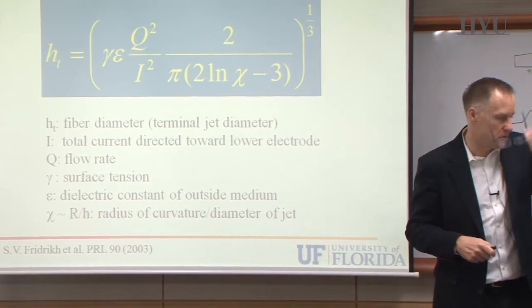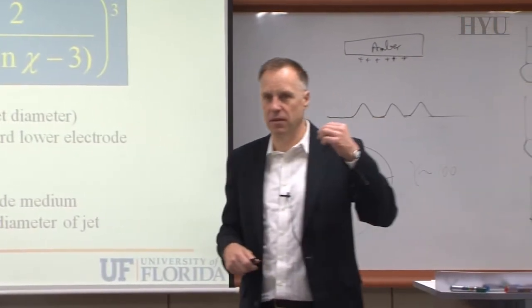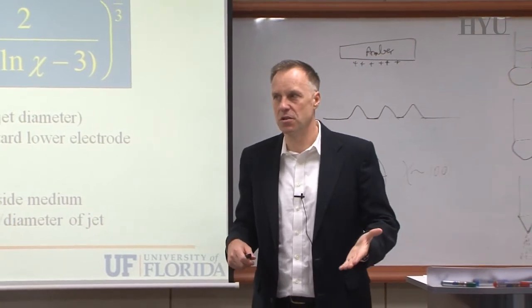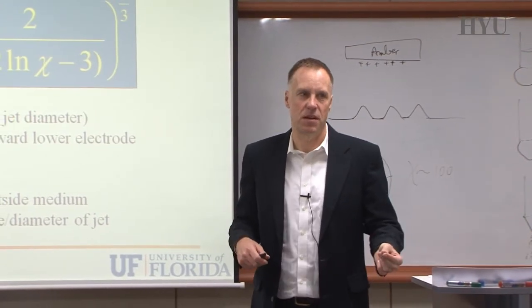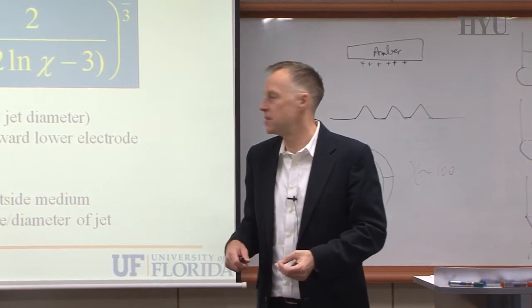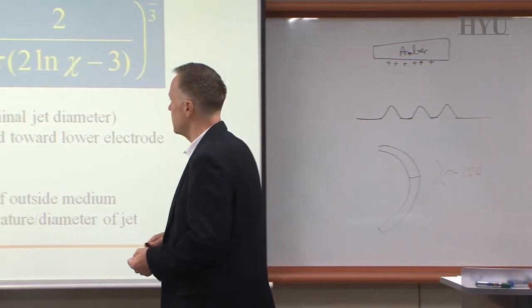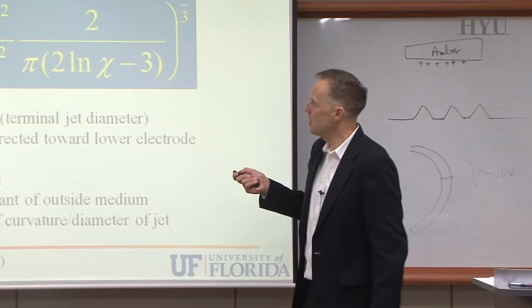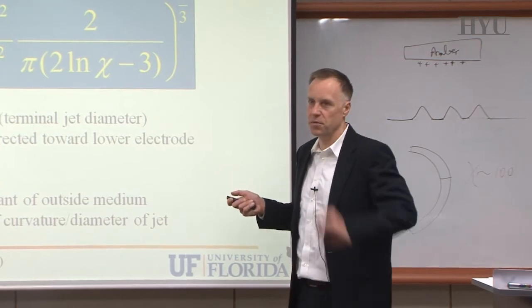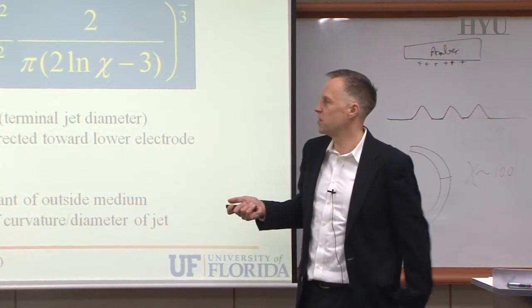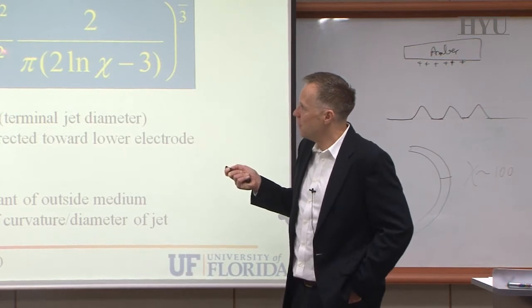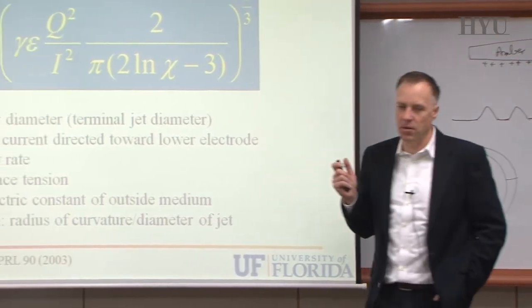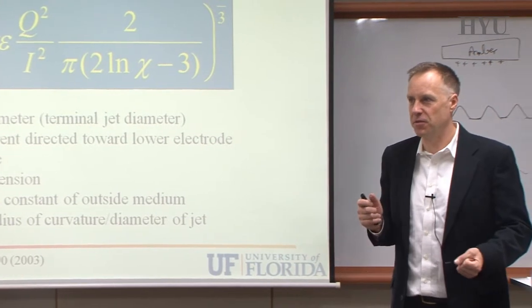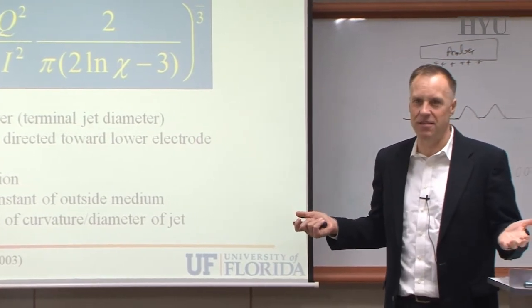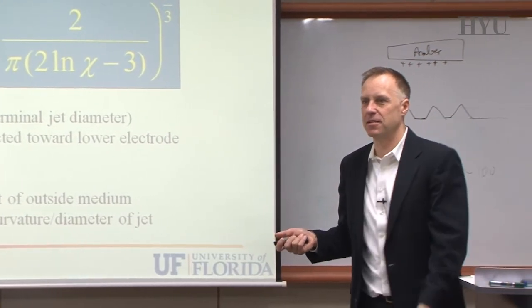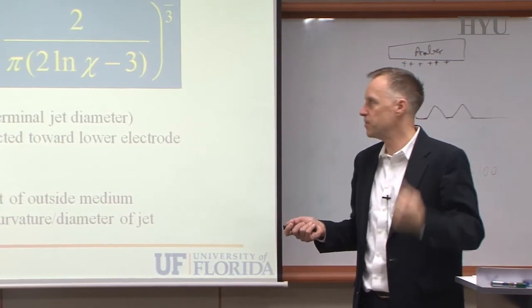Ceramics, you start out typically with ions in solution or with salt systems, but still there are ionic processes available in these systems, and these ions mean you get a high current through the fiber. And when that happens, with a high current through the fiber, you get actually one other phenomenon. One thing is breakdown of the electric field, so electrospinning stops, and then the electric field builds up again, electrospinning starts. So that is a big issue.